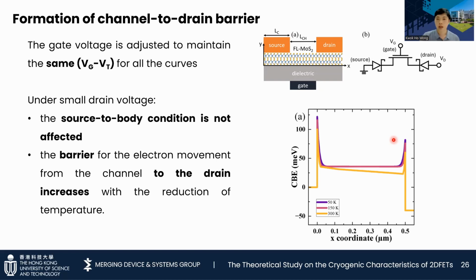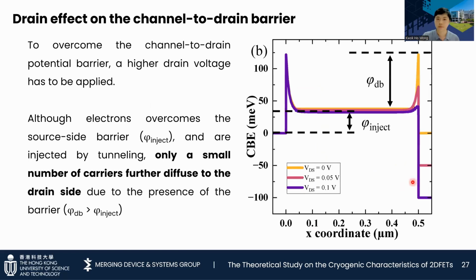It is observed that under small voltage, the source-to-body condition is not affected by the temperature change, while the barrier for the electron movement from the channel to the drain increases. Therefore, under low drain voltage conditions, the carrier conduction is not only limited by the source-to-body carrier injection, but also limited by the channel-to-drain conduction. To overcome the increased channel-to-drain potential barrier, a higher drain voltage has to be applied.